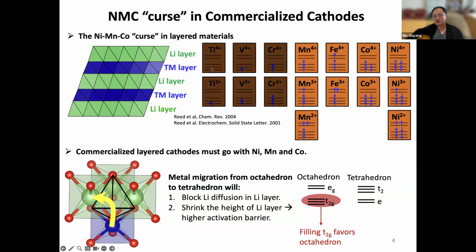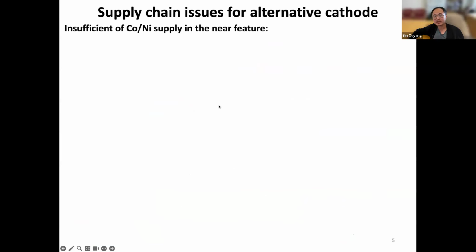So when you oxidize them, when you reduce them, the Jahn-Teller distortion is going to change, right? So hopefully the bond length is going to change significantly. So that also is going to influence the mechanical stability of the layered structure. So eventually you have no other choices. You have to rely on cobalt redox and nickel redox. And manganese 4+ has been used, but you don't want to reduce that in the layered material. So that's actually the reason why people are still working on this limited chemistry.